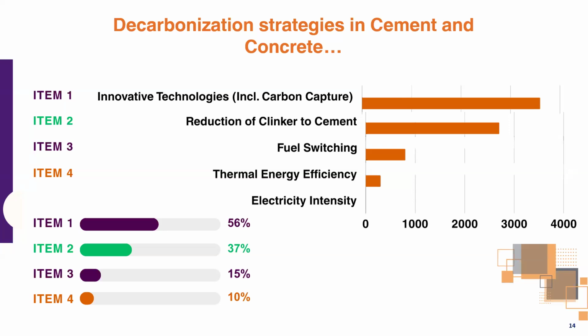The first technology, carbon capture, storage and utilization, can reduce the carbon emission by 56%. The clinker reduction, by replacing it with supplementary cementitious material, can reduce the carbon emission by 37%. The fuel switching means that you can use renewable energy sources instead of coal or crude oils. So if we switch the fuel with more renewable options, we can reduce up to 15%. And finally, by optimizing the thermal efficiency of the cement kiln, and electric intensity, we can reduce 10% of